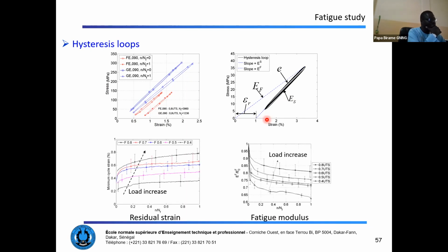So let's look at the residual strain. We can see that the residual strain increases as much as the loading level is increased. And the fatigue modulus, which is the slope starting from 0 strain and 0 stress to the top of the hysteresis loops, decreases throughout the life of the specimen, but is increased depending on the loading level.